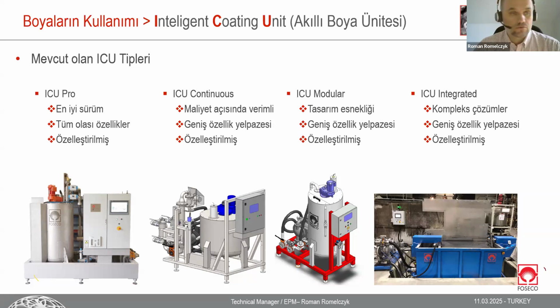And ICU integrated, sorry, a very nice solution. It means that you don't have a preparation tank, but the brain of the system is put directly in the dip tank. So you have some pumps for circulation. It's also connected to the coating on the right side behind the wall. You can see the coating and the container with the coating. Thinner, it's water here. So water is from the system. It prepares a batch of coating in the dip tank, and during the usage, the system takes care to prepare other small batches to keep exactly the same setup level in the dip tank. So for 8 hours, 10 hours, that doesn't matter, as long as you want.